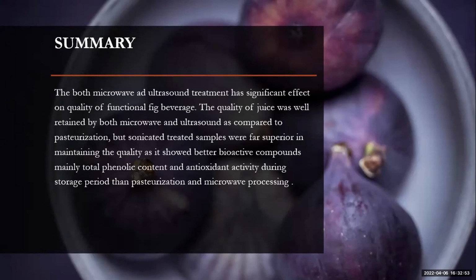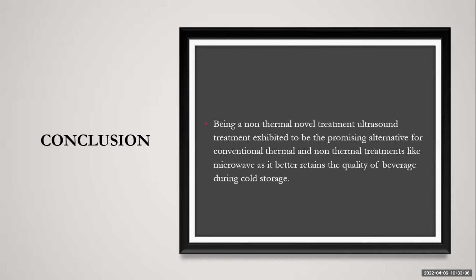But sonicated samples were far superior in maintaining quality, as they show better bioactive compounds, mainly total phenolic content and antioxidant activity during the storage period, than pasteurization and microwave processing. So the conclusion is that, being a non-thermal and novel treatment, ultrasound treatment is a promising alternative to conventional thermal treatments and non-thermal treatments like microwave, and it better retains the quality of the beverage during cold storage. Generally in industries, pasteurization is used, which can be replaced by ultrasound and microwave treatment to retain the qualities of the fruit.